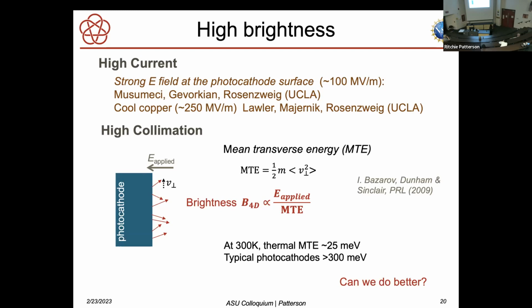And then you also want high collimation as the electrons emerge. So here's a photocathode, and here there are little velocity, momentum vectors coming off. And there's a component of their velocity that's parallel to the surface, perpendicular to the direction we want them to go. And we define something called the mean transverse energy, just 1/2 mv squared, where we're taking the bad component of velocity. And we would like MTE, the mean transverse energy, to be small. And in fact, you can show that the brightness, the thing we're trying to maximize, is just proportional to the electric field divided by the mean transverse energy.